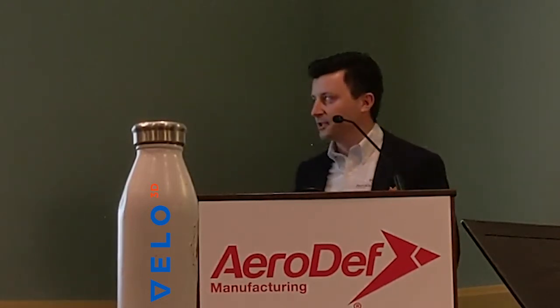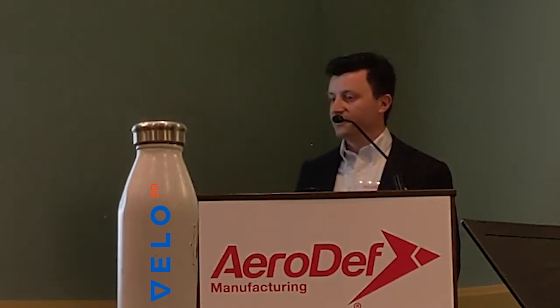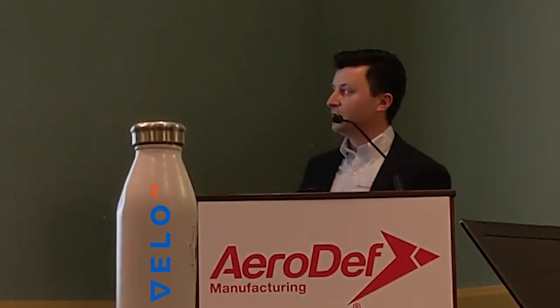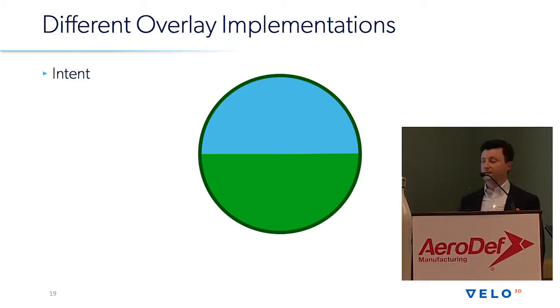And when you're looking for throughput optimization, there's kind of two parts to this. There's laser assignment, how you break up a part to be assigned to the two lasers, and then scheduling. Another way that we've seen people approach the laser assignment, which is also an interesting way to get past some of the limitations of the previous scheme, is, if you're on a dual laser system, to run the core split up between the two lasers, but to then run your contours with a single laser. And this is interesting because you actually don't break up the contours, right? So you don't have this overlay mismatch where the contours are broken up. And it's kind of a clever way to get around this.